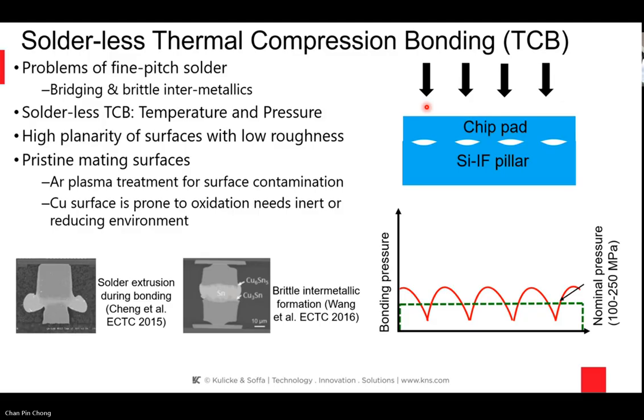And as Chanpan has mentioned, this requires high planarity of surfaces with low roughness and pristine mating surfaces. We get those pristine surfaces either through argon plasma treatment to remove surface contamination, or more recently with hydrogen plasma treatment to reduce surface contamination. But the point to make here is that the surface is prone to oxidation and needs some sort of an inert or reducing environment. So as you apply pressure, these surface asperities are reduced. Let's go to the next chart.